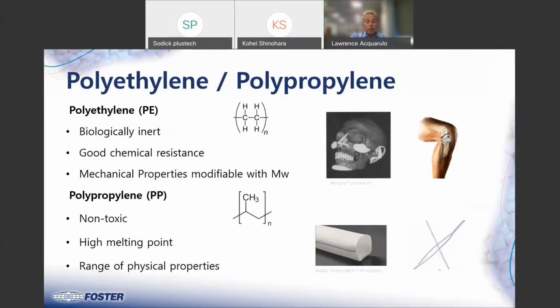Polyethylene, simple structure. The molecular weight is very important on polyethylene, and you'll see that in a lot of hip implants where they're using high molecular weight polyethylene. Most of those are not melt processable by the means that we probably process, but they're formed in different ways or machined. But it's an excellent material, biologically inert, good chemical resistance, good mechanical properties, and you can tune the molecular weight for the application. They are finding more applications in some of these facial structures and just for trauma.